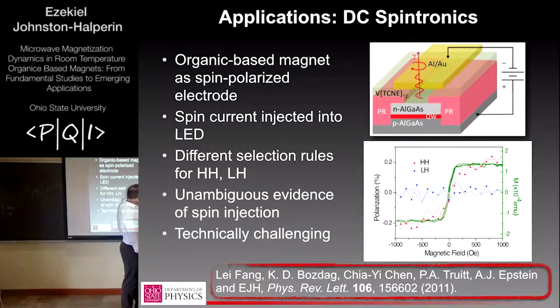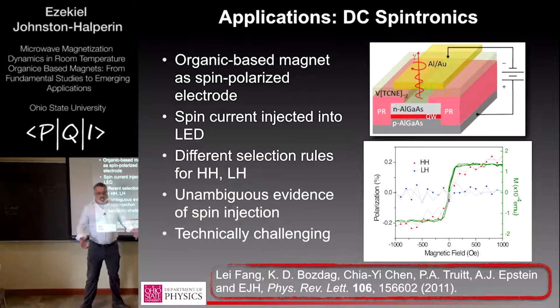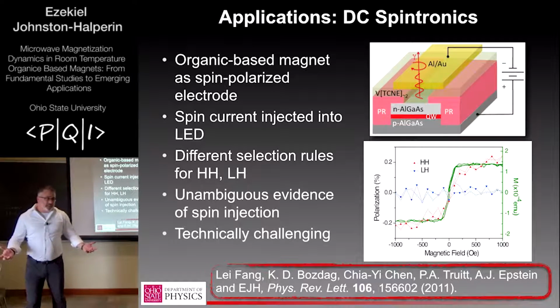For detailed reasons that aren't probably worth going into, the heavy hole and the light hole give different polarization response. You can see here, though, in the heavy hole band that you get a polarization response in red that mimics in green the magnetization response of the film, so it acts as a spin injector.